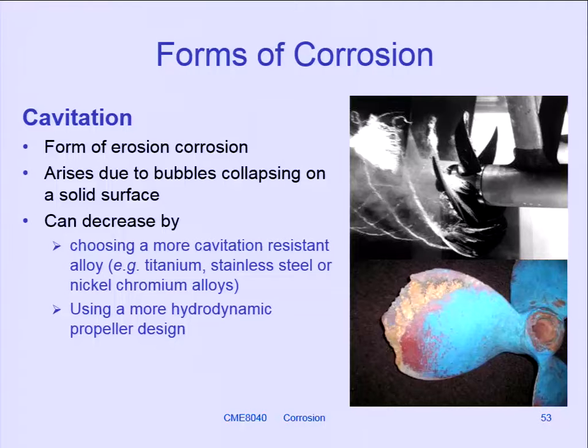So if you over rev, if you turn a propeller or impeller too quickly in a fluid, then you'll begin to get shear between the solid rotor and the liquid, and the shear velocity is enough for void formation to occur in the solution. So these aren't gas bubbles forming, these are holes forming in the solution because the blade is cutting past it so fast. And those voids are unstable and they collapse explosively. That provides the mechanical impact on the metal surface, and therefore it provides the mechanical extra to the corrosion to give you cavitation corrosion.